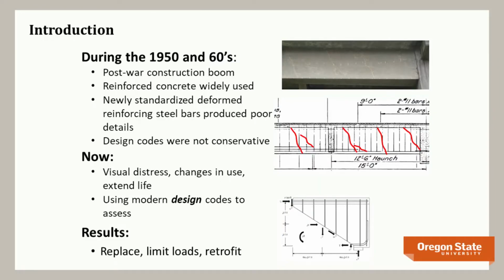You'd had all kinds of bends and anchorages to make sure those bars were going to be able to be developed. But when we now have these beautiful deformations, we could terminate them with straight bars. We can get rid of all those bends. At least we thought we could. At the same time, we were overcounting what the concrete could do, particularly for what its shear contribution was. And so as a result, we were putting more concrete in, less steel, and the steel we were putting in wasn't well detailed. And as a result, we've got some problems and deficiencies in those bridges, things like cracking and diagonal tension cracking in particular. And now we go to evaluate them with modern design codes, and we find they just don't pencil out.